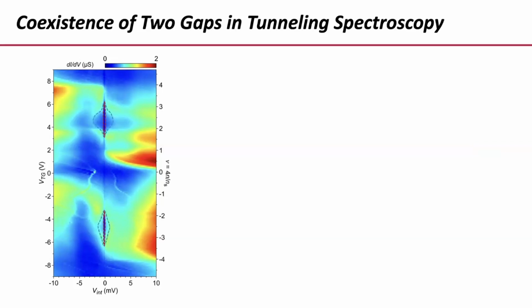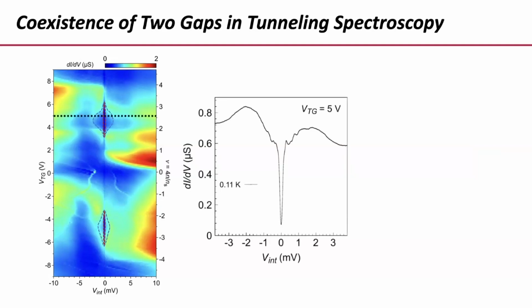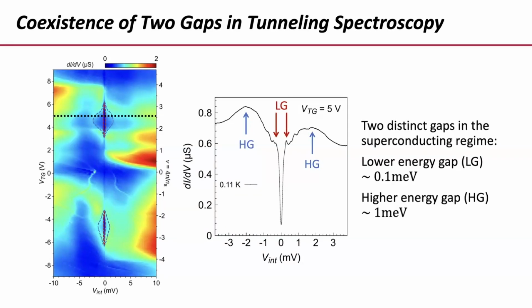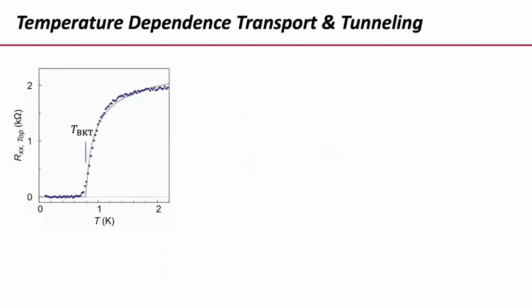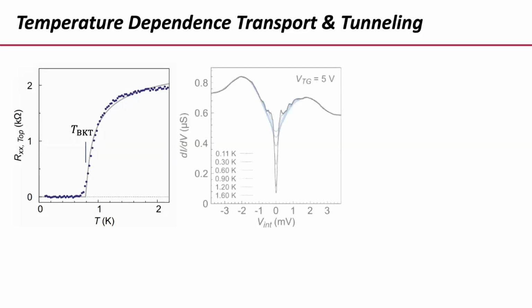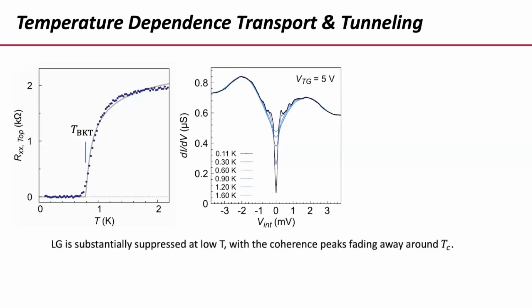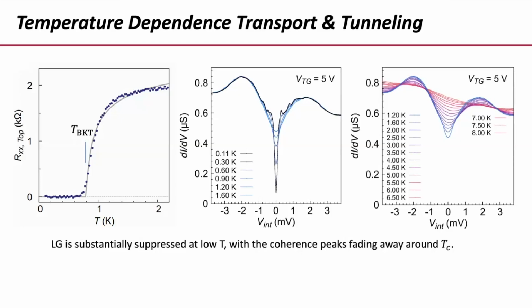I'll just go fast. So we have 2 regions with 2 types of gaps. Okay. If you take a trace, you have actually a low energy gap and a high energy gap, 2 distinct features. These 2 gaps have energies about 10 times different. If you do transport through the same structure, you can see at what temperature the resistance deviates from 0. And if you do tunneling spectroscopy, you can see that the inner gap very rapidly disappears with temperature, okay? Whereas the higher energy gap has a very slow dependence on temperature. This thing disappears on the scale of TC. This one takes much longer, okay?